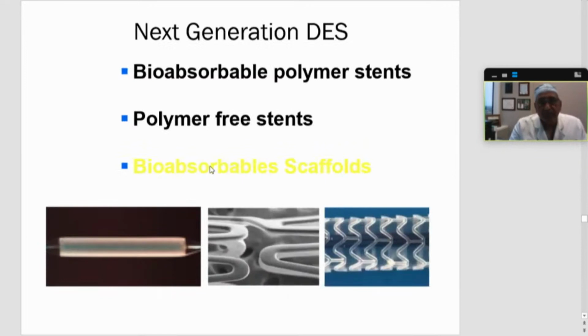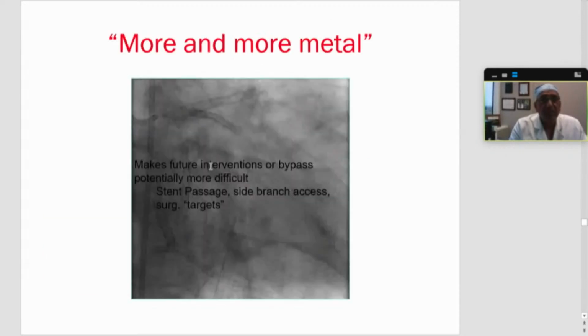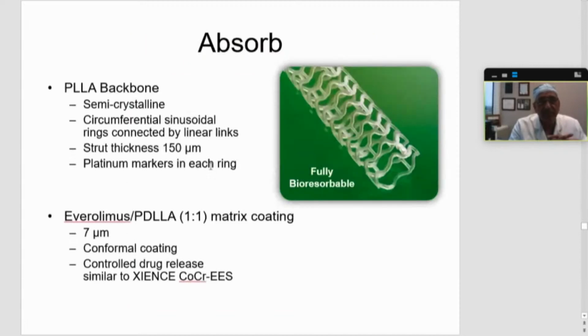And then the bioabsorbable scaffolds. I think right now that science is on hold for a few reasons, but I think it's a very interesting idea because you have to get tired eventually of all these stents which we keep on placing in those coronaries. So the Absorb design has a PLLA backbone. It's semicrystalline. It is circumferential sinusoidal rings connected by linear links. The strut thickness is a little bit big. It is 150 microns, and there are platinum markers in each ring.